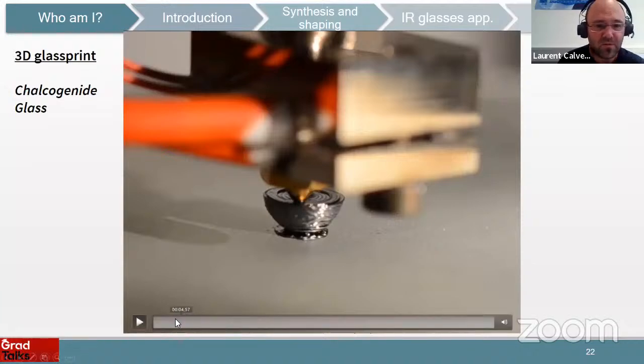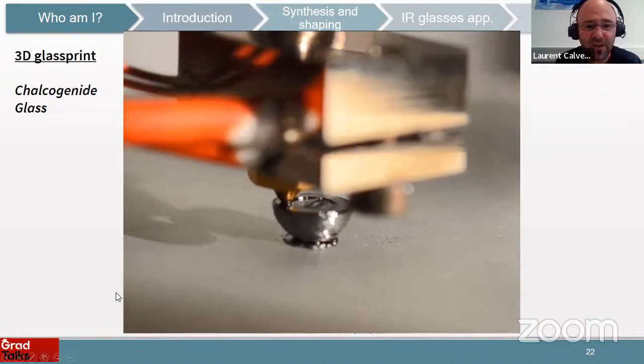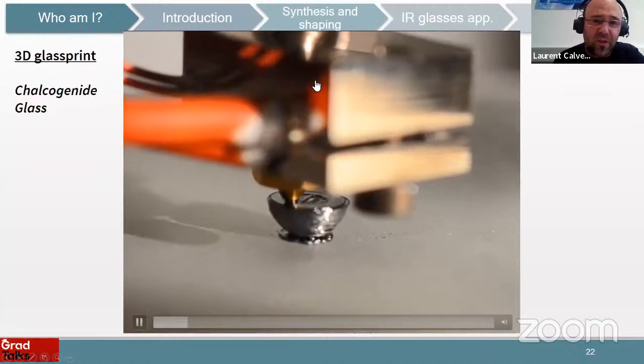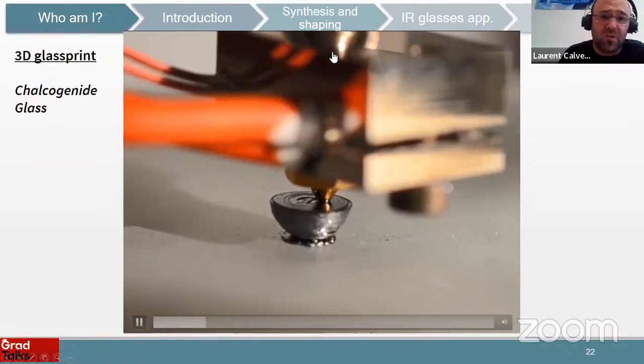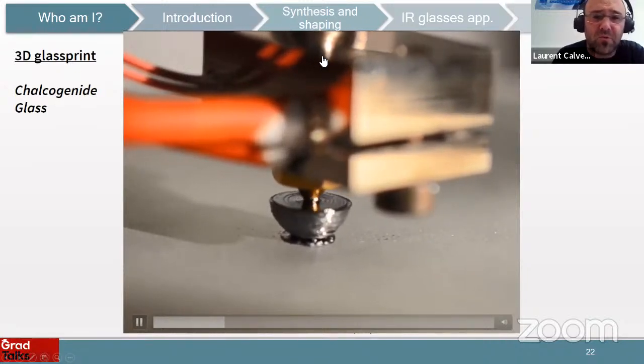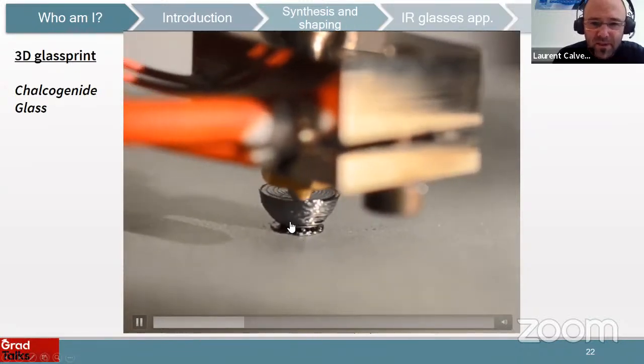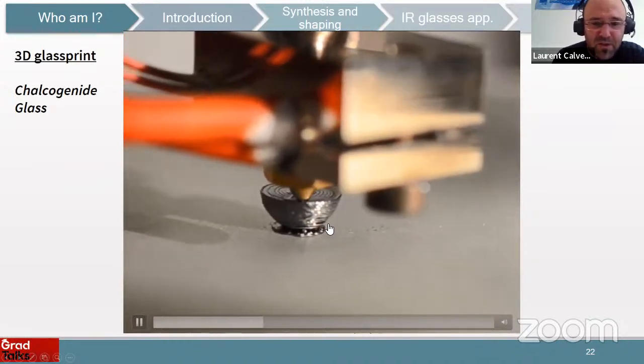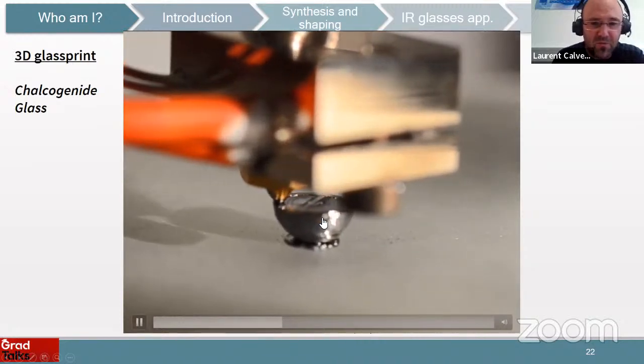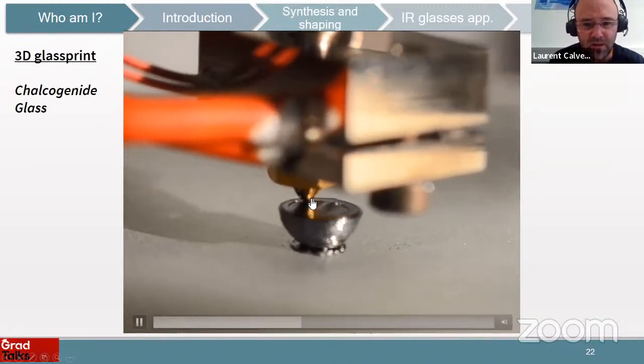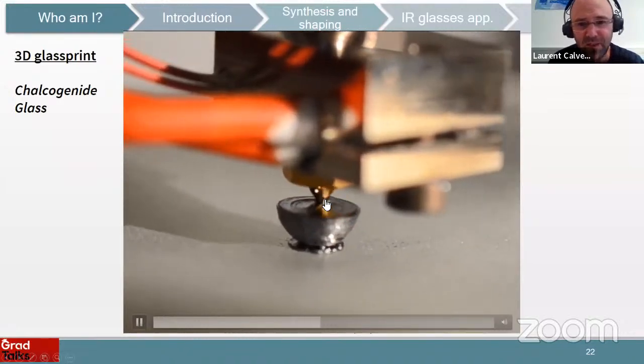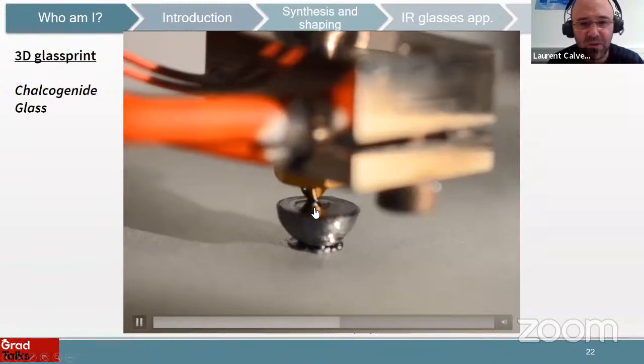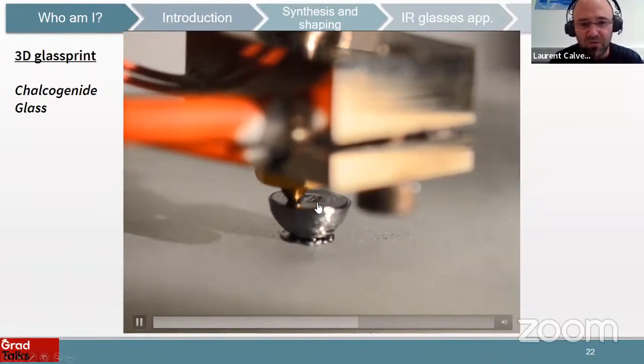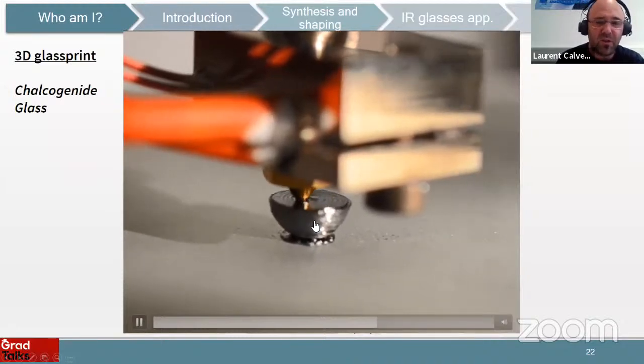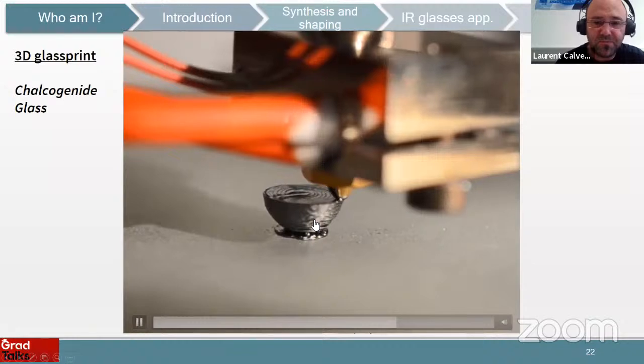And here also is a small movie to show you how to make 3D printing of chalcogenide glass. So on the top, you have a furnace, which is just above the glass transition temperature. So it's around 300 degrees C. And then you print it. You can see the design will depend on what you want to get at the end. You will use a specific code to print it. And what you can see, it's still liquid, and in few seconds it becomes solid because of the glass transition temperature. And at the end, you will be able to make the shape you want.